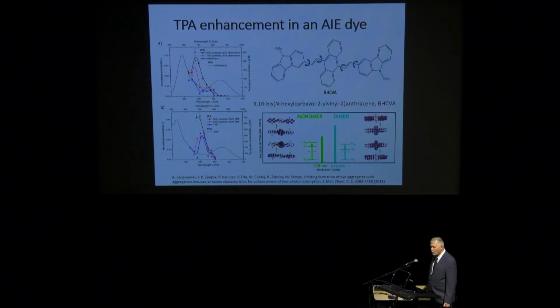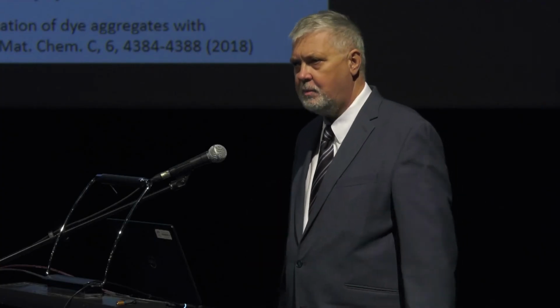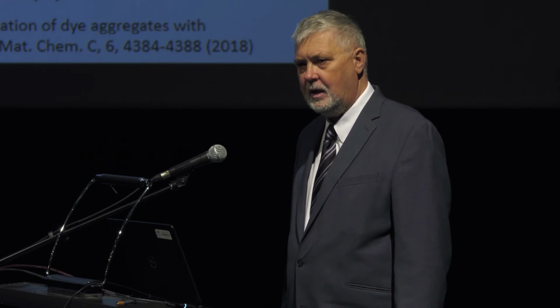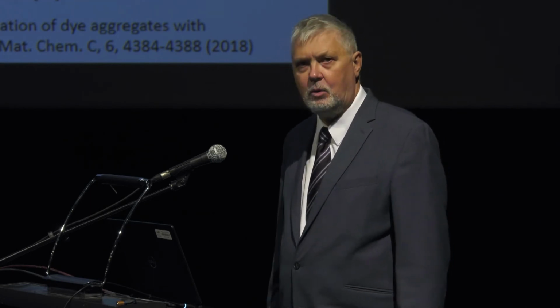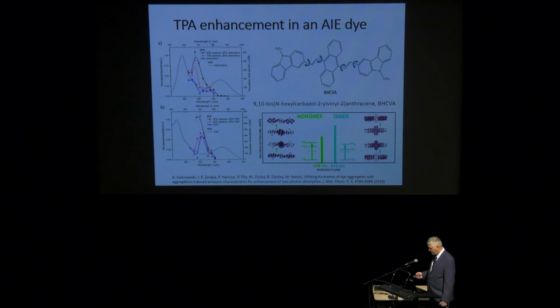So what we did in one of the papers was we proved that such dyes, these AIE dyes, not only increase the emission quantum yield, but they also increase the two-photon absorption cross-section. And there are good reasons for that. It's rigidification of the structure, it's interactions between the planes of the dyes, it's all explained quantum chemically. So yes, aggregation can lead to quite sizable enhancements of nonlinearity.